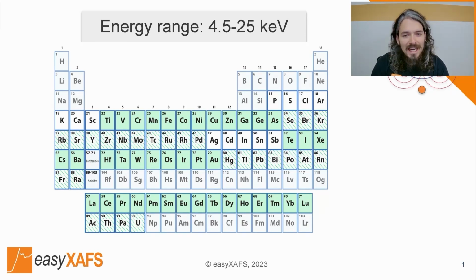So as you go to higher energy, there isn't a sharp cutoff, but the X-ray flux is reduced. And that's from lower generation from the X-ray tube and also reduced efficiency of the Bragg diffraction from the crystal analyzer. So like the example I showed earlier, a nickel K-edge measurement could be measured as quickly as just a couple minutes, while if you want to measure the palladium K-edge, the measurement would require several hours.